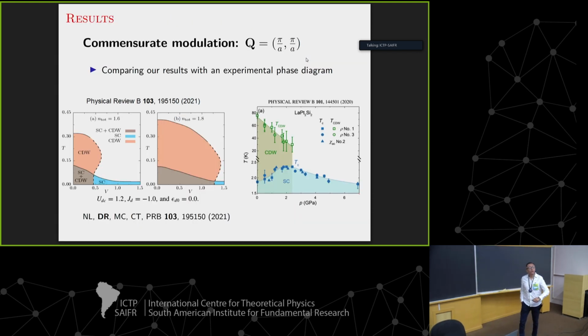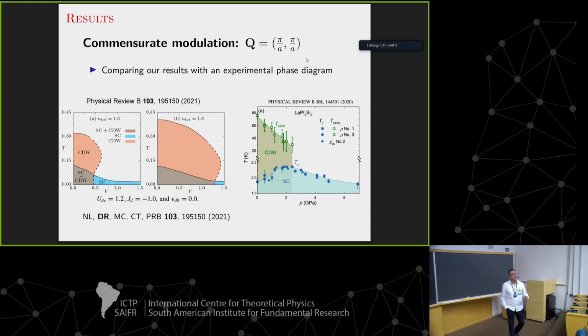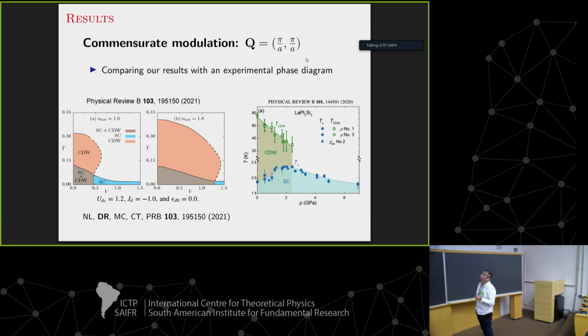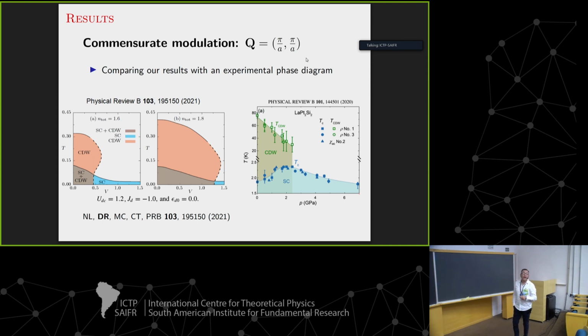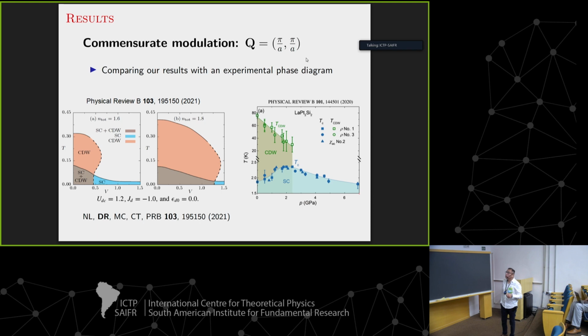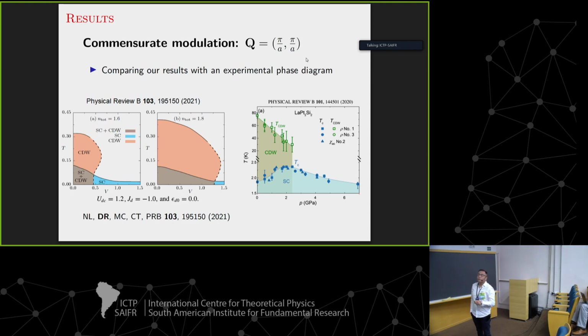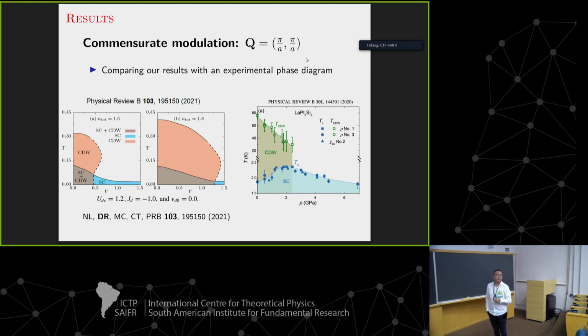Okay, let's go to the results. First, in the commensurate regime. Remember, we are in 2 dimensions, it's a square lattice, so the modulation wave vector is pi over the lattice parameter. So just take a look first at this. This is an experimental phase diagram, a very nice experimental phase diagram for a CDW compound, lanthanum platinum 2 silicon 2. And we can see here that for high temperatures and weak pressures, there is a well-established charge density wave order, but at low temperatures, there is a kind of coexistence between the CDW phase and superconductivity, right?